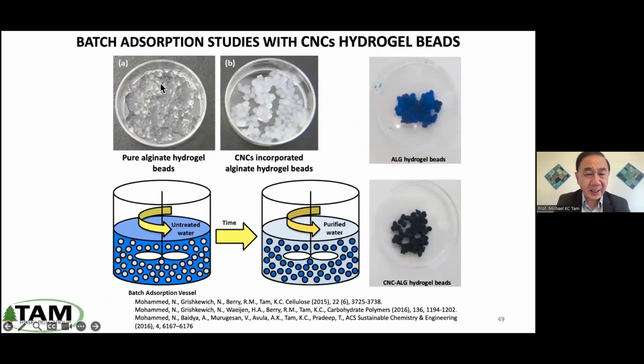So as you can see, here is pure alginate, it's not robust. When you put CNC, you get much better properties, and the white nature is because the CNC is now impregnated into this alginate system, right? So our goal is to put this into a solution with contaminant, in this case methylene blue dye, and to extract those dyes from the bulk water into the beads. As you can see on the right, if you have pure alginate, the removal of the methylene blue is not as good compared to when you have this high surface area CNC impregnated into the alginate bead. And this result shows that we have very good performance.